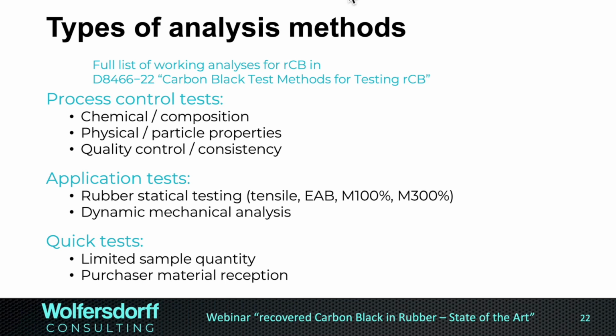Analysis methods. There are 3 types of analysis method categories I see. A full list you will find in the ASTM document 8466 of last year, carbon black test methods for testing recovered carbon black. I would see 3 major categories. The recovered carbon black industry, like the gentlemen in this webinar, need process control tests. So this will be chemical compositional tests for the consistency of the material. It might be physical and particle properties like the particle size to test whether the milling was sufficient.